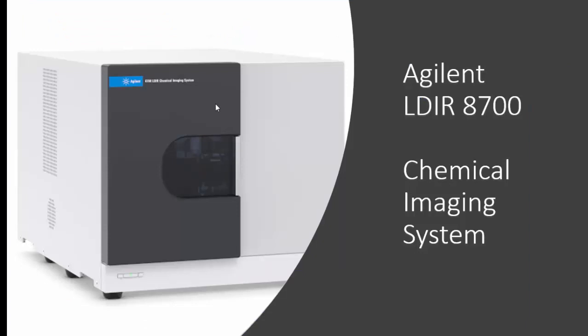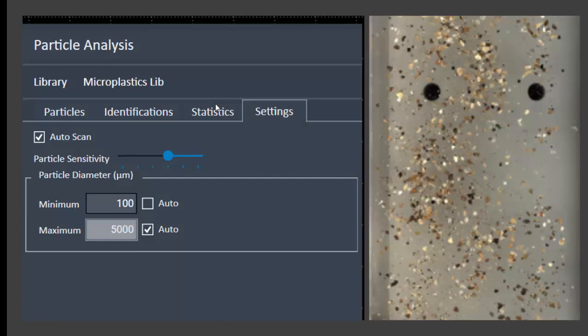After working with the micro Raman method for a good part of a year, we were able to obtain the Agilent LDIR 8700 as a chemical imaging system that was originally designed for pharmaceutical analysis. However, it has demonstrated itself to be very beneficial for particle analysis as well. The first step is to take that slide that we previously plated and insert it into the instrument, and the first thing we select is the particle sensitivity. We would pull up a library. The microplastics library that we've assembled has common components such as polyethylene, polypropylene, LDPE, HDPE, Teflon, and other common rubbers and different types of plastic polymers.